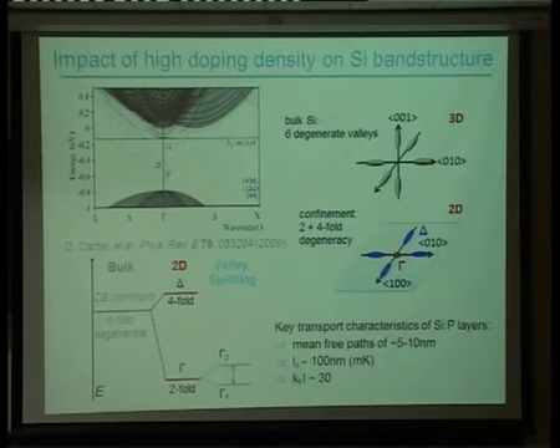So what does that mean for the semiconductor? It basically means that we're conducting here through a very highly disordered system. The phosphorus atoms are sitting in the plane of where the electrons are traveling. As a consequence, the mean free path is about 5 to 10 nanometers. The phase coherence length, on the other hand, is very long, around 100 nanometers at millikelvin, and kF l is around 30. So you've got this highly conducting metallic state, which is essentially a disordered metal, which is where we're going to be passing the electrons through.